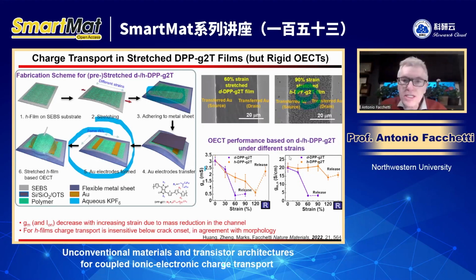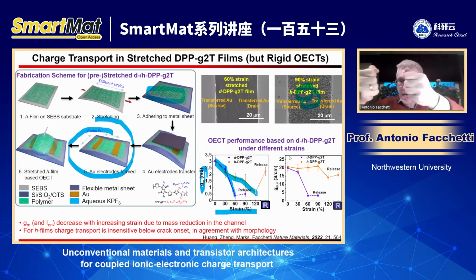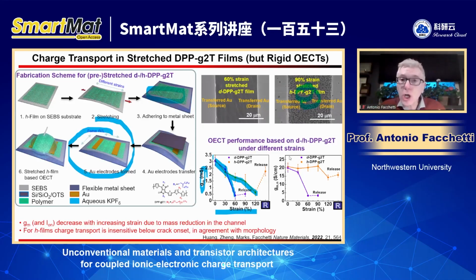What you see here is the transconductance current when you stretch. For both the dense film and the honeycomb film, in all cases, the transconductance decreases, and this makes complete sense. The reason is that I stretch the film and put it between the source and drain, which are exactly the same. So you stretch, you have less mass, you have less ions, so the